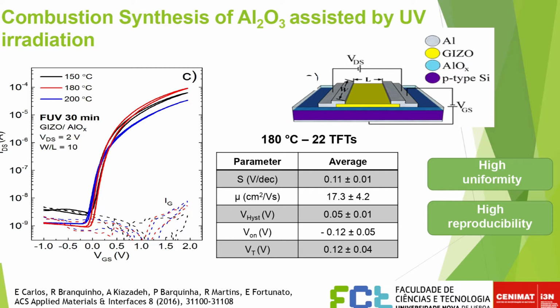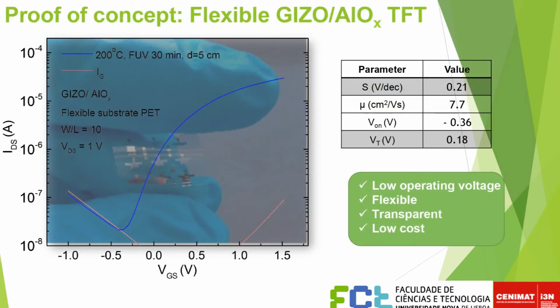So again, for example, we test in that case not only one single device, but 22 TFTs, and they are quite good in terms of reproducibility, because this is also an issue when we are trying to compare physical technologies with chemistry technologies. Again, this was the same result where we deposit the TFTs over a flexible substrate.